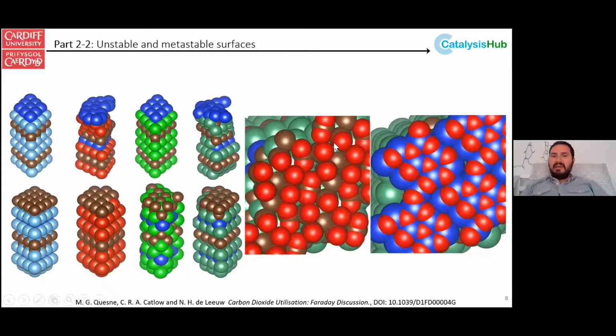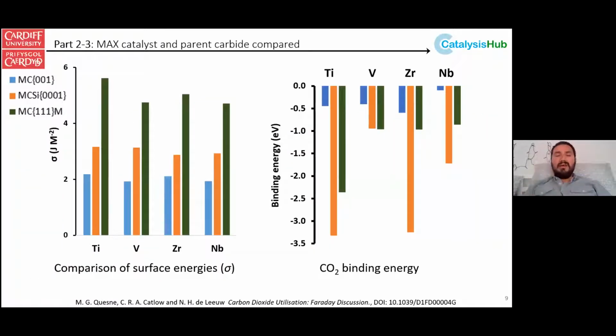The other thing that I would say is that just to prove how unstable these were, when we had any kind of oxidant on the top, we got major reconstruction with both the carbon and the silicon free layers. Okay, so when we looked at the properties of these materials, we saw that in actual fact, the basal 0001 plane of the silicon carbides was slightly higher in energy than what we saw with the monocarbides.